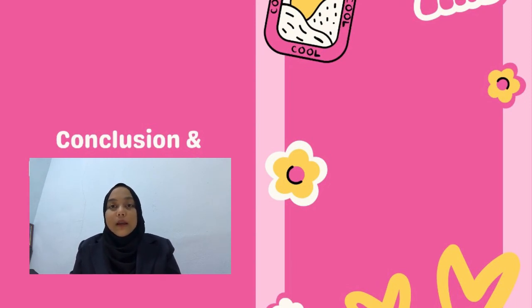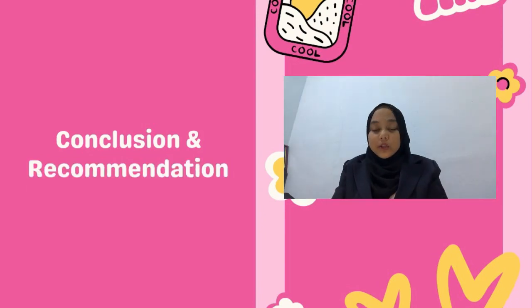The BCZY-LSCF, which is known as the symmetrical cell, was modified through surface modification by using ZrOCl2 aqueous solution. This is done by dip coating method, where the result shows that the aqueous solution has the ability to reduce oxygen vacancy on the surface. Dip coating method plays an important role in the surface modification, where the pellet is submerged into ZrOCl2 8H2O.